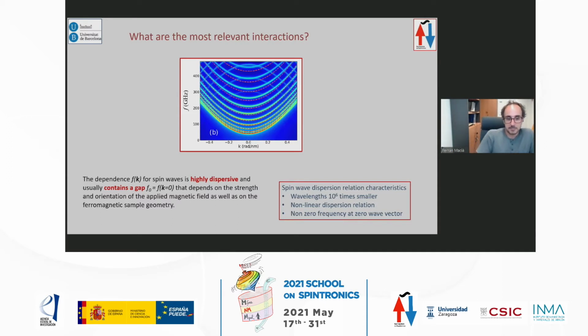So summarizing a little bit what I've said so far, what we have with spin waves is that the dependence of frequency versus K vector is highly dispersive. This is something we've seen, and it can become much more complicated. And also there's a gap. You see, there's a gap here, and this gap can be controlled by the applied field. We saw that in the previous talk, and Tim mentioned that it's quite interesting. You can shift the resonance frequency by applying a magnetic field.